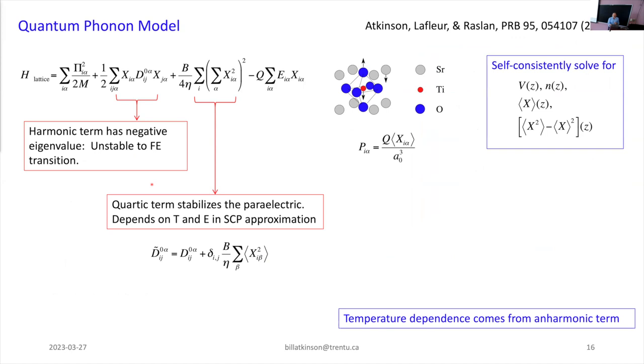Okay. So the quantum phonon model, this is an old model from the 1970s that we resurrected. It's a model for this one phonon mode. This mode is characterized by a displacement x. You can think of this displacement as the relative coordinate between the titanium and the oxygen. So imagine the center of the oxygen octahedron and the titanium atom, and then there's a relative coordinate between those two points. When x is zero, the polarization is zero. You can relate x to the polarization by this expression here. Q is just an effective charge. It's a fitting parameter. You can get it by modeling the dielectric susceptibility. We have a kinetic energy term for the mode, and M here is an effective mass. You can get that by fitting the phonon spectrum. And then this second term here is a quadratic term, so it's your spring constants for your model.